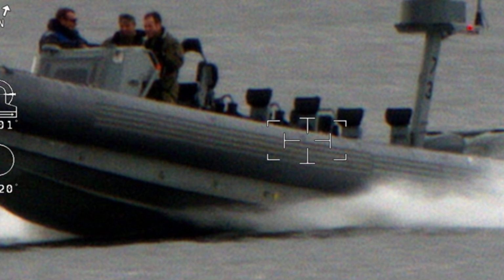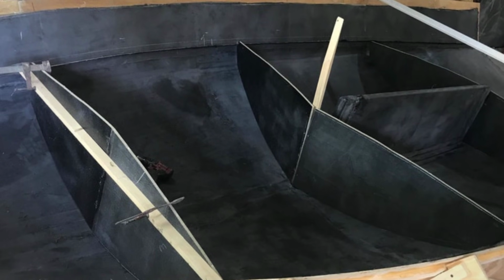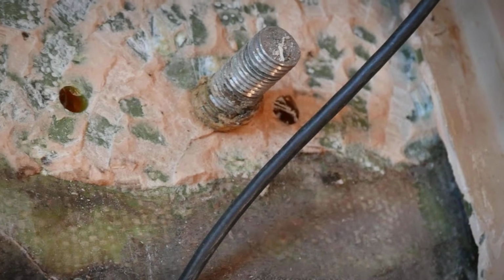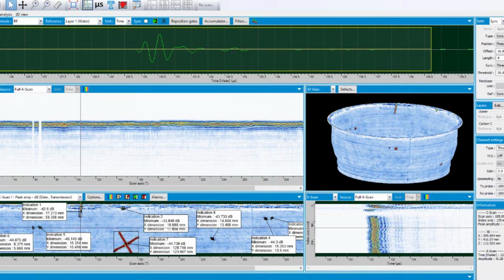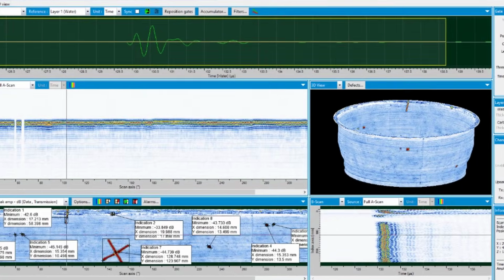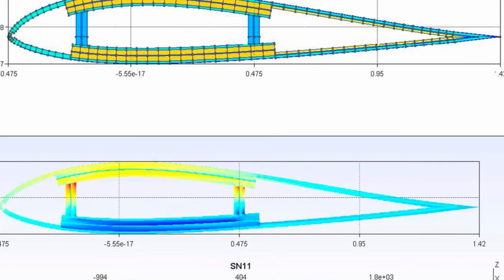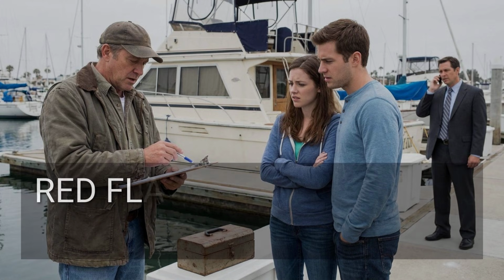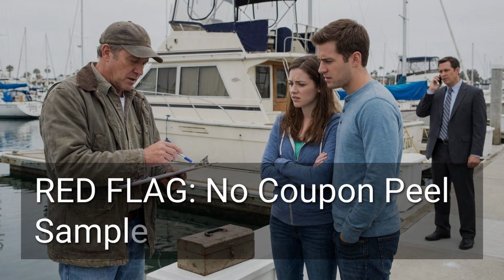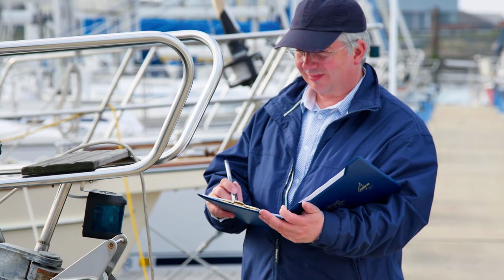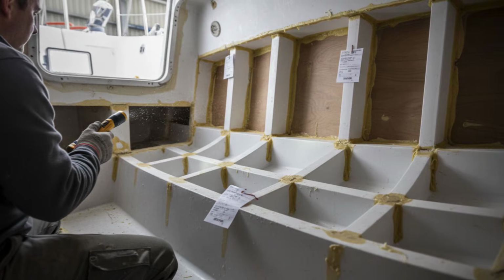No paperwork, no deal. Bring a surveyor equipped for non-destructive testing. Infrared thermography can reveal hidden delamination. Look for hotspots along grid ribs, especially near the mast step and keel bolts. Ultrasonic C-scan maps bond thickness; flag any region under 0.5 millimeter. If the seller objects to a coupon peel sample, that is another red flag. Serious buyers get serious evidence.